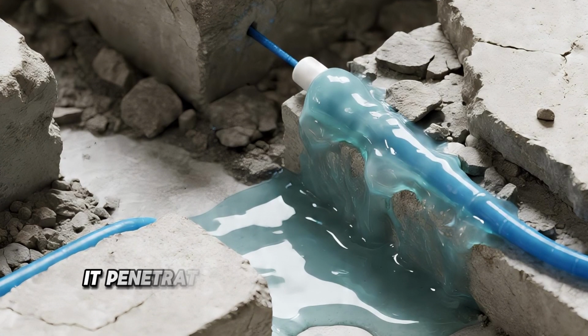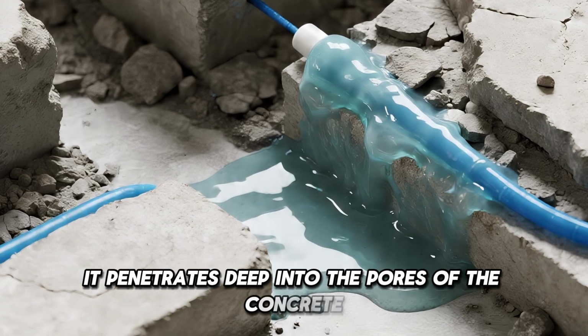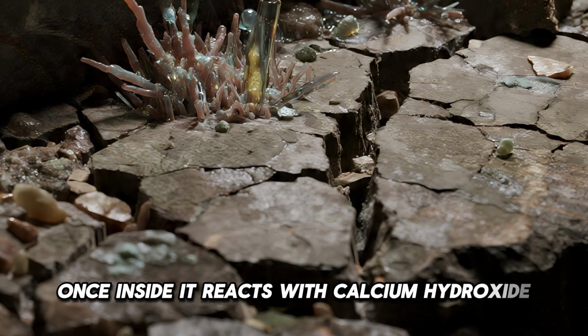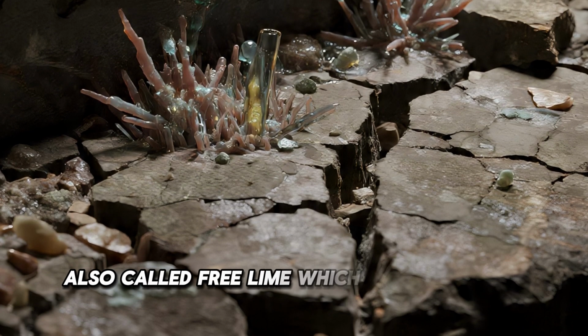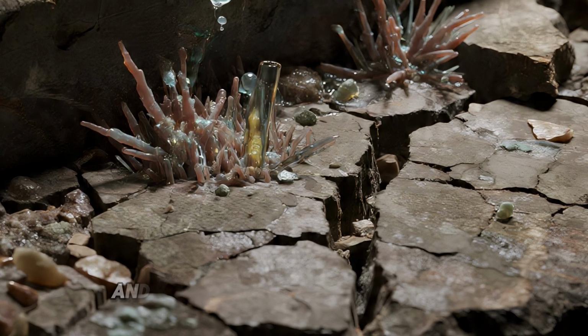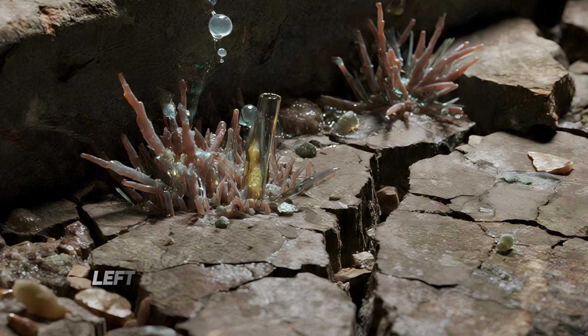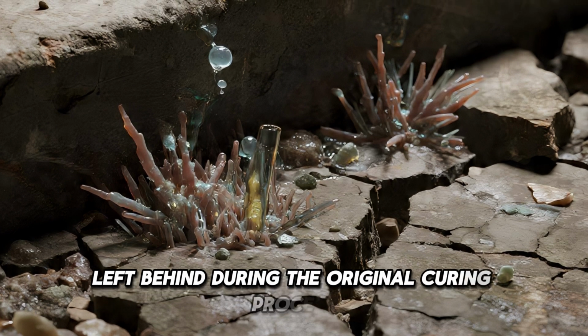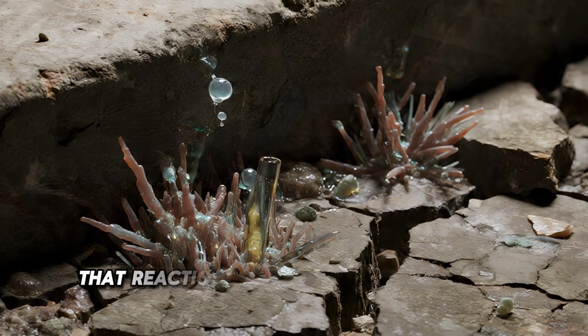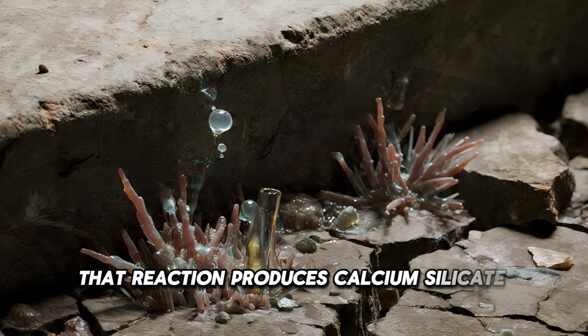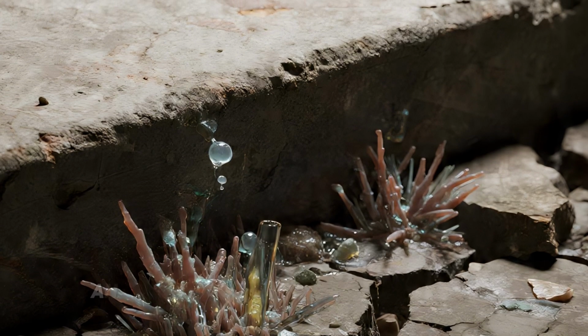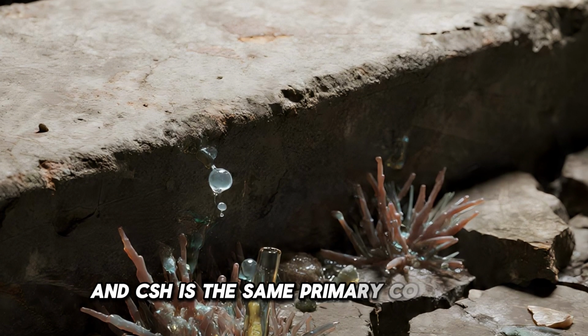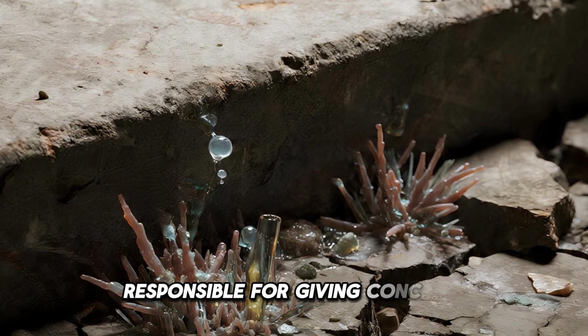Instead of simply sitting inside the crack, it penetrates deep into the pores of the concrete. Once inside, it reacts with calcium hydroxide, also called free lime, which is a naturally occurring and structurally weak byproduct left behind during the original curing process. That reaction produces calcium silicate hydrate, or CSH, and CSH is the same primary compound responsible for giving concrete its hardness and strength in the first place.